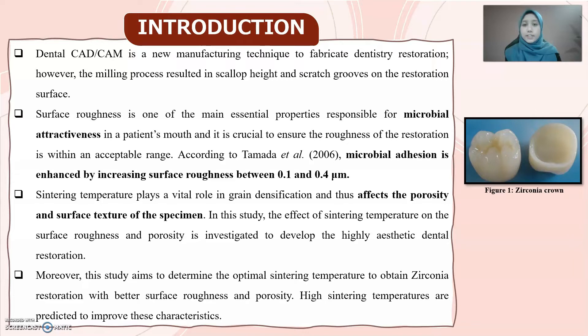Dental CAD/CAM is a new manufacturing technique to fabricate dental restorations. However, the milling process results in scallop height and scratch grooves on the restoration surface. Surface roughness is one of the main essential properties responsible for microbial attractiveness in a patient's mouth, and it is crucial to ensure the roughness of the restoration is within an acceptable range. According to Tamada, microbial adhesion is enhanced by increasing the surface roughness between 0.1 and 0.4 micrometers.